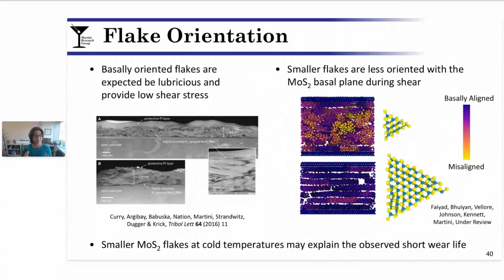So lastly, inspired by previous research which has shown that the orientation of MoS2 lamella with respect to the basal plane and with respect to sliding is critical to its performance, we evaluated the orientation of our flakes. This is shown graphically here on the right, where the color indicates the alignment of the flake. Yellow means the flakes are not oriented well with the sliding direction, and purple means they are oriented quite well. And already you can see just visually, the small flakes are less aligned, which should correspond to less good performance as a tribological system. So cold temperatures, smaller flakes potentially explains the reason we see the shorter wear life in those cold temperature experiments.